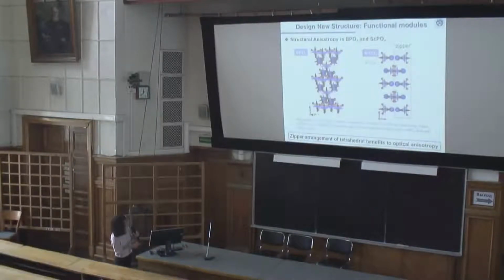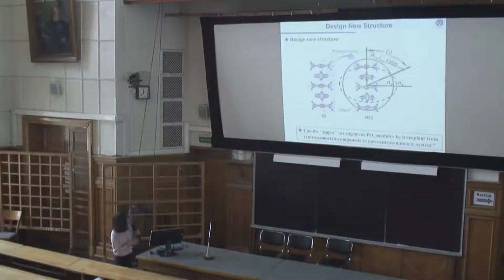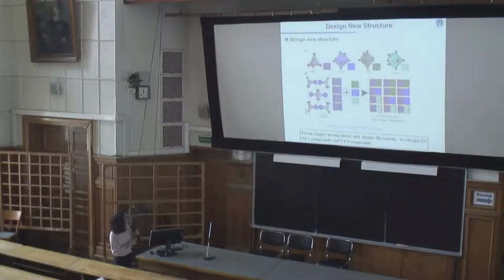And there are two compounds as a comparison. For these compounds, the theta is not easily changed. And for these compounds, the theta is 0, and this makes the largest birefringence. So we call this kind of arrangement a zipper arrangement. But this zipper arrangement only exists in centrosymmetric structures. Can we transplant it to non-centrosymmetric ones? So for this, we introduce different cations here.